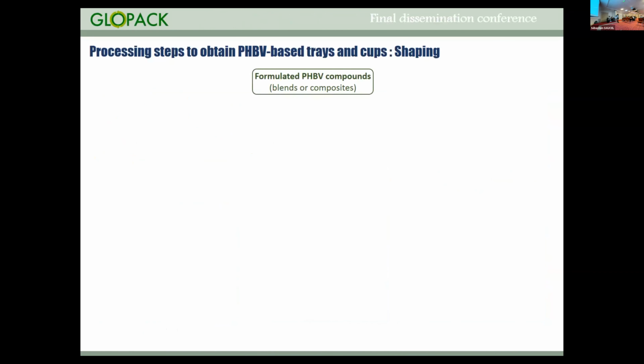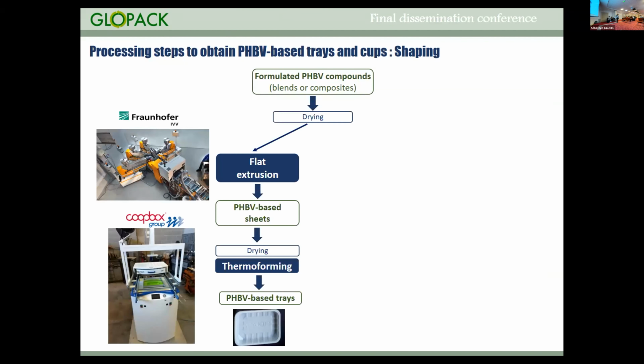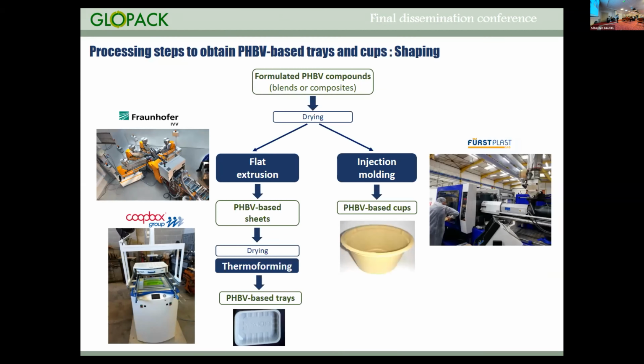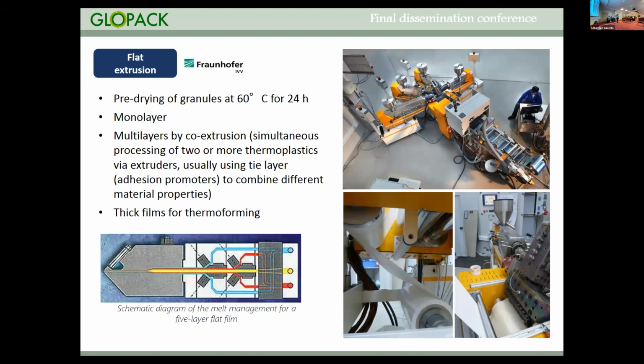Okay, and when we have these formulated PHBV compounds, we have investigated 2 routes. The first route was the production of thermoform trays by Coopbox, but you can see that it's not possible to produce thermoform trays directly from the compounds. You have an intermediate step, which is a flat extrusion, and it was performed at Fraunhofer. The second route was injection molding, and this was the expertise of Fürst Plast. In that case, you can produce cups directly from the compounds. So Cornelia is going to give you some details about this flat extrusion, which was quite tricky to obtain sheets.